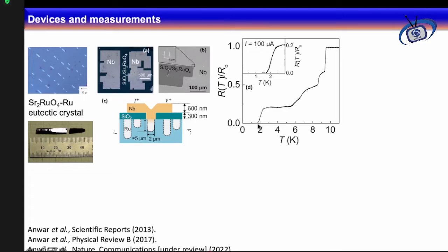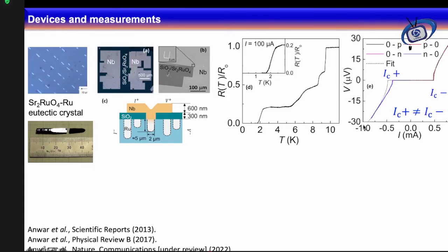And in this junction, we can observe very clearly a zero resistance state, meaning the superconducting state that you can see in this resistance versus temperature graph. Now here, if we measure the IV curve, then you can see here as well what is going on, that we have this superconducting IV curve.